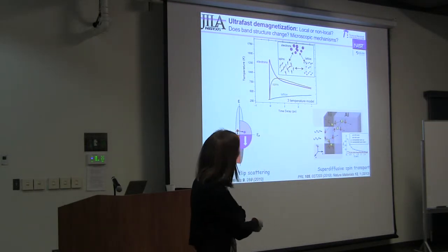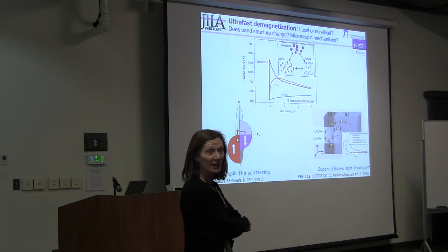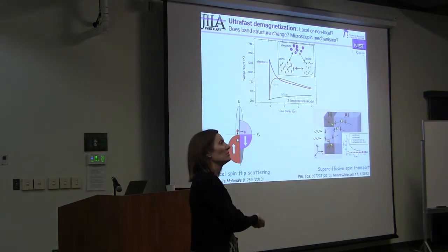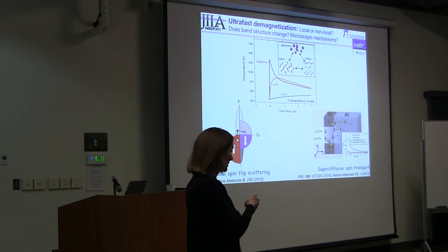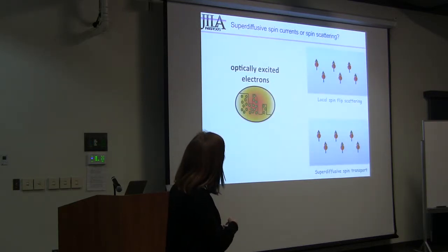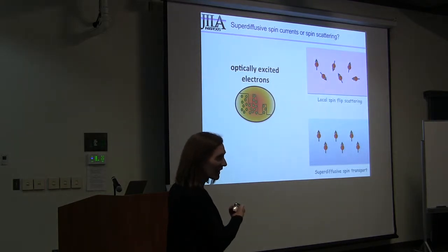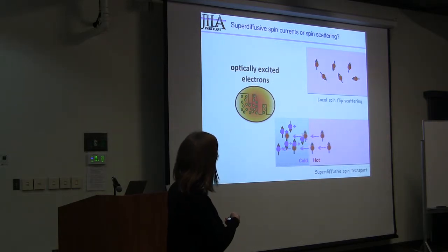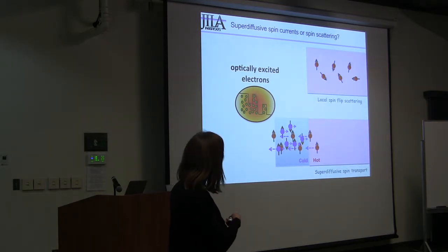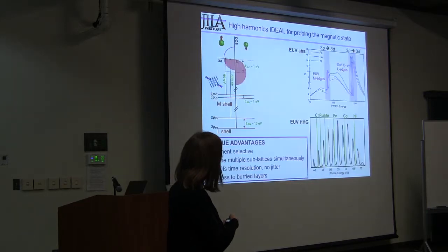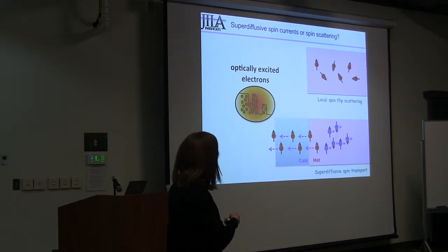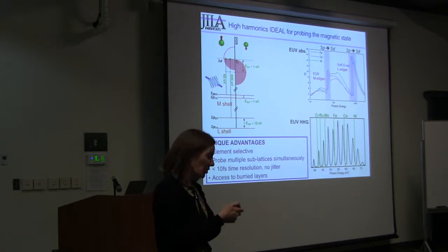Of course, this is a non-local mechanism and the other is a local mechanism, so we figured maybe we can see the difference between these two mechanisms by doing an experiment. This is my experimentalist cartoon: in one mechanism you heat the material and you have local scattering, and in the other you heat the material, a spin polarized hot current leaves the region and your return current is cold. Those are very different. So how can we read the magnetic state and try to see, yes?